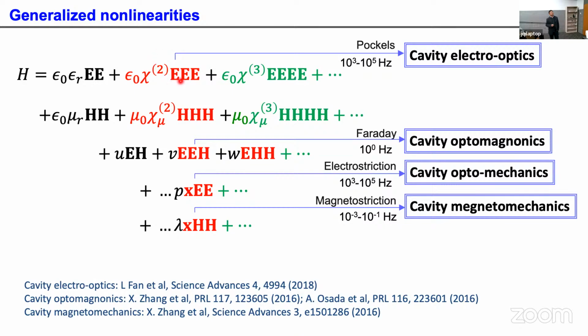If you look at Chi2 nonlinearity, that will be the E fields coupled together of the coupling modes. If you talk about the Pockels effect, one of the E fields is a microwave mode. That is basically what we utilize for this Pockels cavity electro-optics, microwave to optical conversion. We utilize this term here, Chi2 nonlinearity. And you can also write the magnetic interaction term. You also have a similar Chi2. Those are relatively weak, and you can replace one of the E fields with the H field. And this is the Faraday effect.